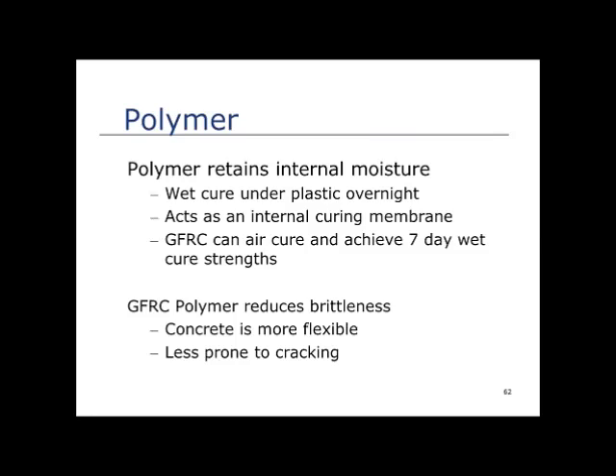The other secondary benefits of the polymer are that it significantly reduces the brittleness. In structural terms, it's called the modulus. So the higher the modulus, the stiffer it is, the more brittle it is. Imagine a piece of spaghetti: before you cook it, when it's dry out of the box, it's very brittle. It's a very high modulus. And when you cook it, it gets soft, and now it's very bendable. It's very low modulus. Well, the polymer helps to soften it, so it allows the concrete to flex more without cracking. When you have fewer cracks, you have fewer callbacks, you have fewer problems with your customers. So you're more likely to get paid and to keep the amount of money you hope to. So although it's an expensive ingredient, it's a very, very beneficial ingredient.